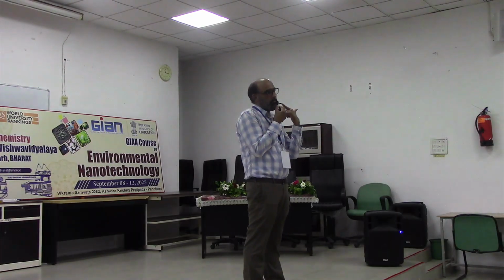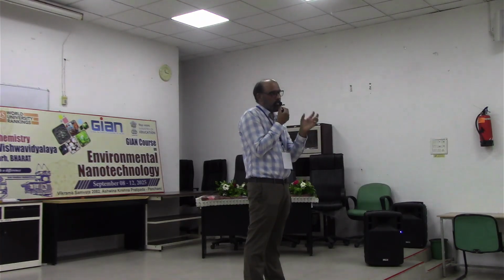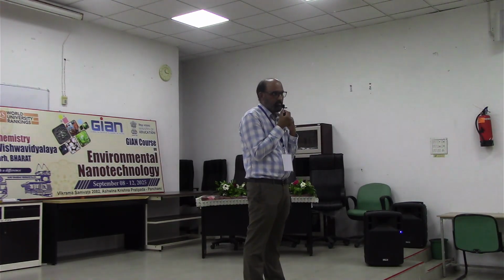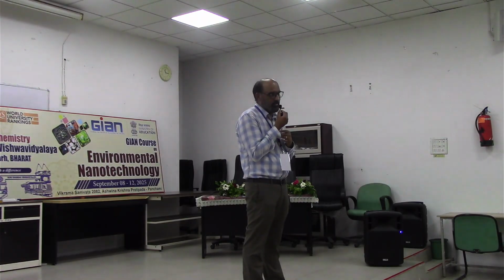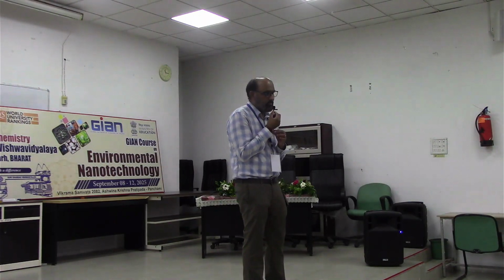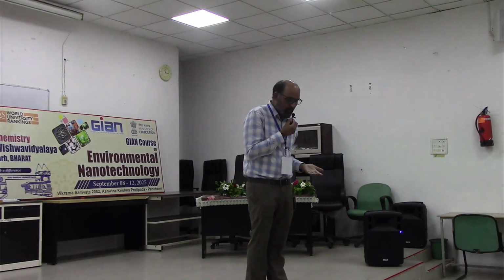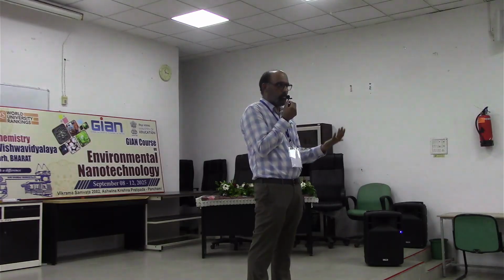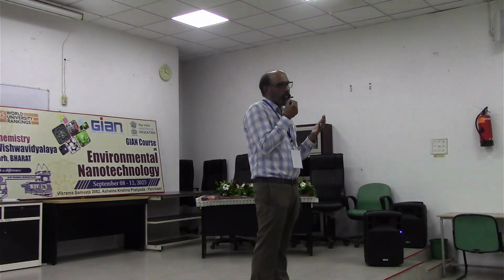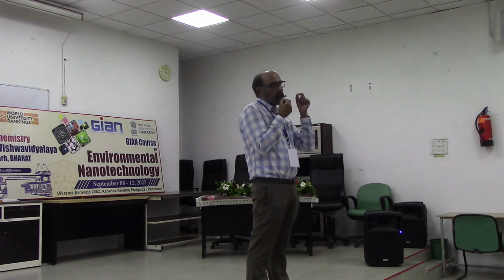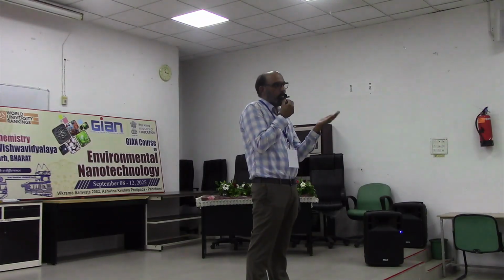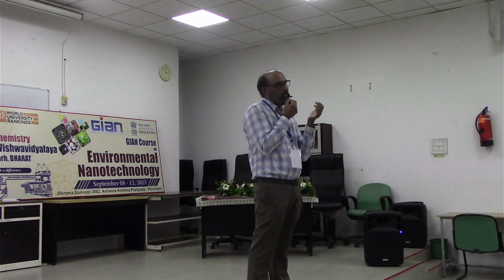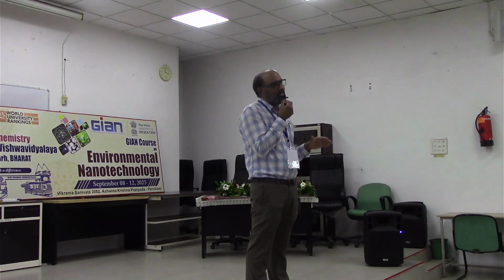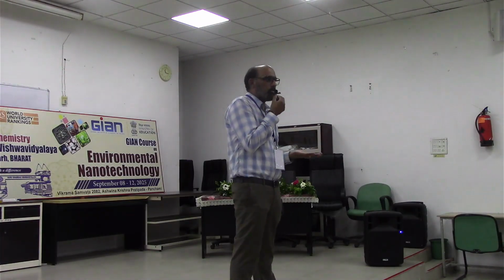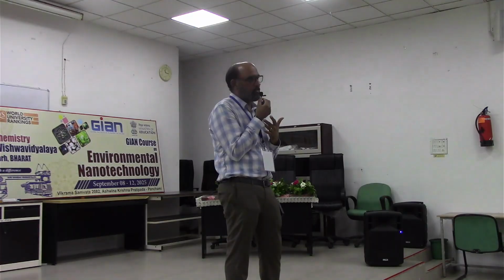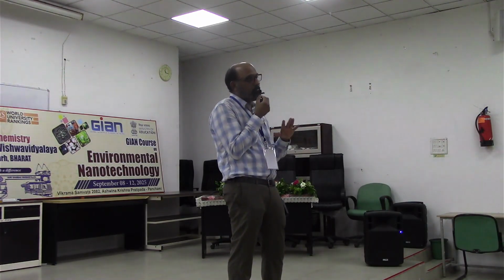In our case, we used polyvinyl pyrrolidone and cellulose acetate. It's a mixture. Other polymers you can also take, but it depends on which application you want. This PVP is totally biodegradable. PVA, polyvinyl alcohol, also is highly biodegradable. But if you want conductive films, you may have to use PVDF, polyvinyl... I forgot the rest of it. It depends on which application you want. If it is an electrical application, you may not get a biodegradable material. But there are a lot of biodegradable films.